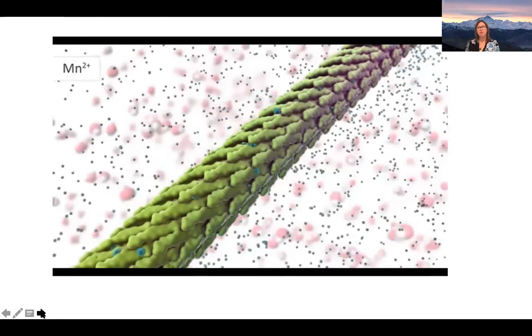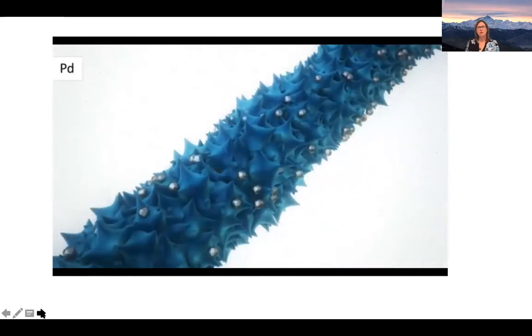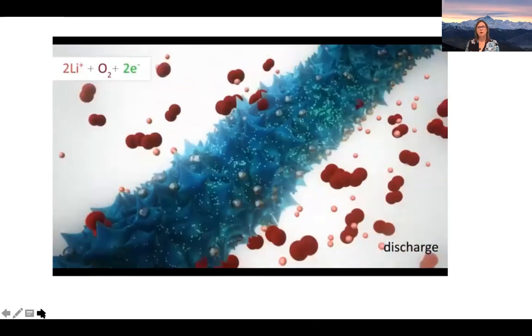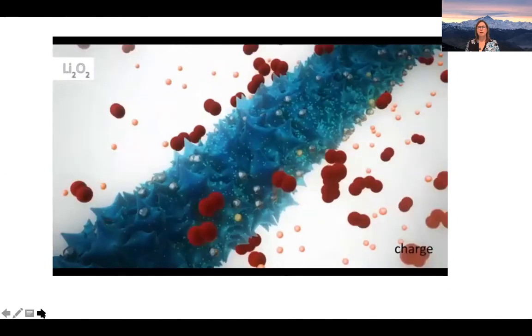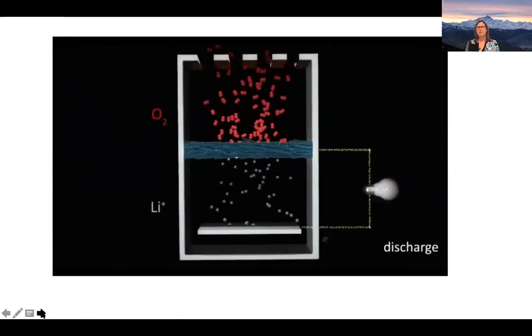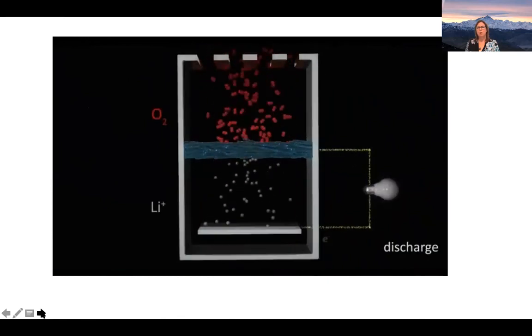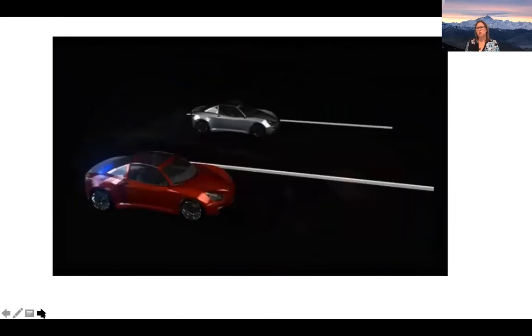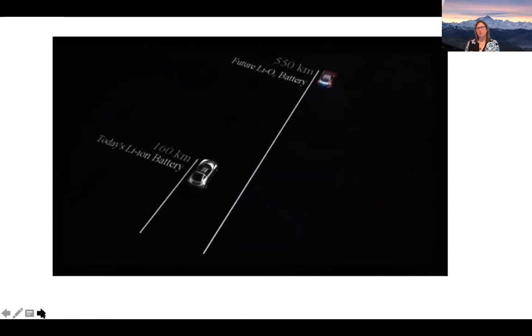You have a virus, it's in water, you grow manganese oxide, and you give a little palladium. And this is a reaction, the reaction's going really quickly. But the idea is that it's going to be much lighter weight because you're going to be using oxygen from the environment as part of the reactant for your battery electrode.